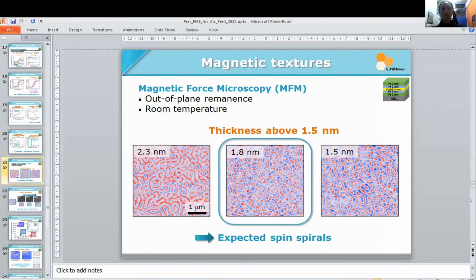But to be able to know if we have skyrmion textures or not, we look at the magnetic texture directly through magnetic force microscopy, MFM, which was performed at out-of-plane remanence and at room temperature. For all thicknesses above 1.5 nanometers, of course, we have the expected spin spirals. Here I was showing you the result for the unpatterned thin film. All the results are similar for the ones in nanodisks. For 1.8 nanometers, you have the expected spin spirals.